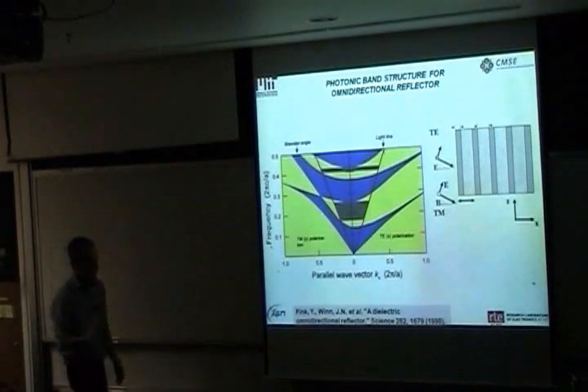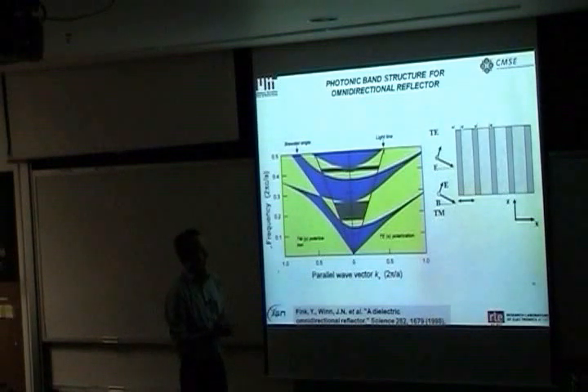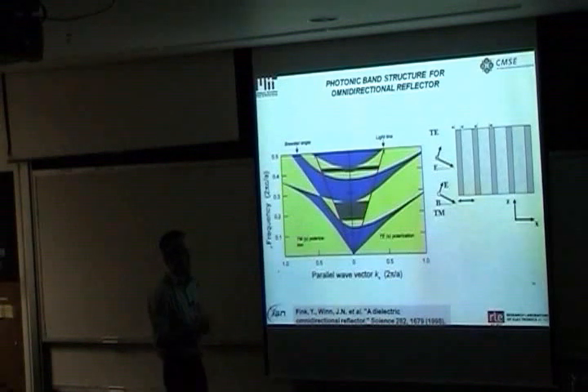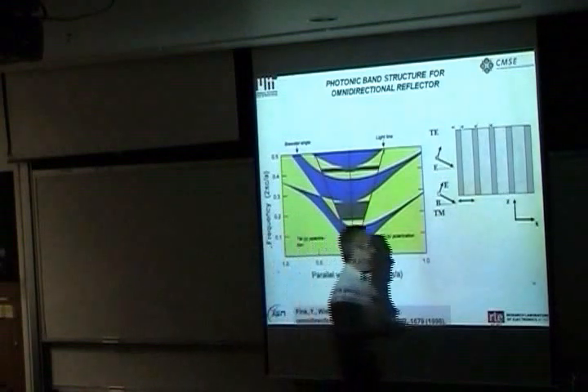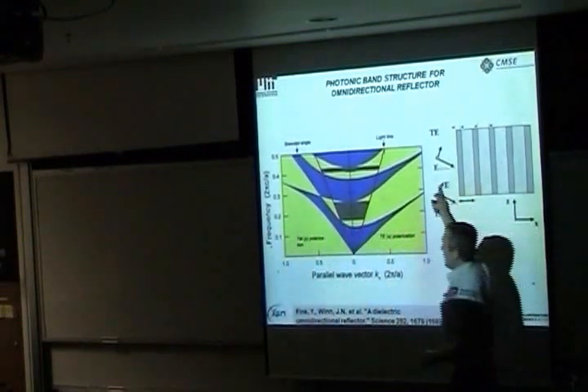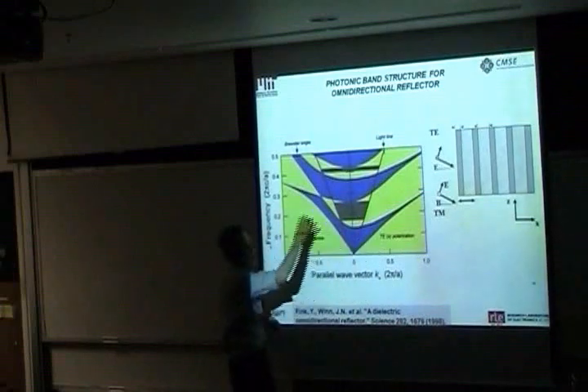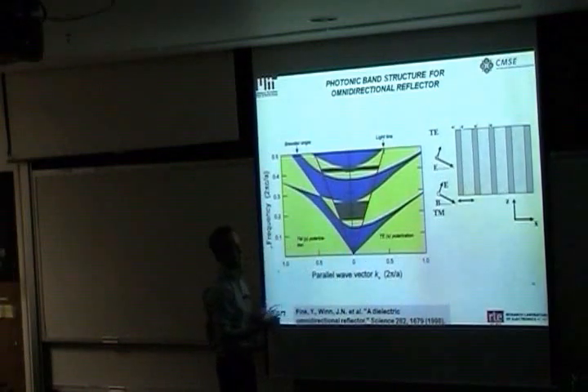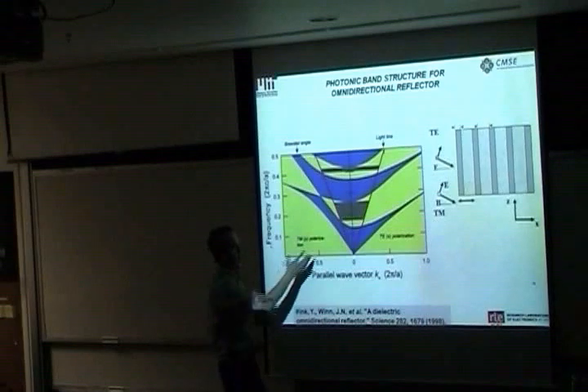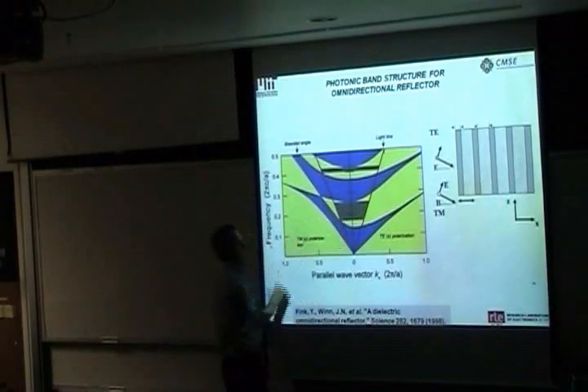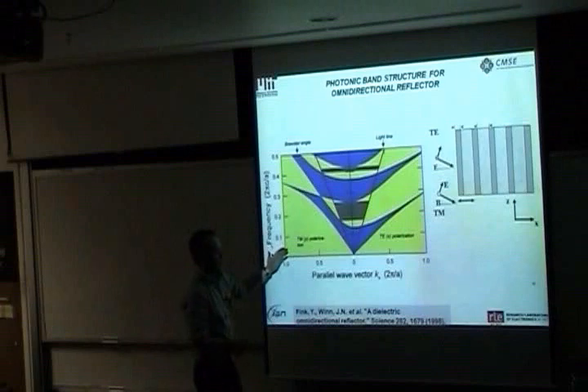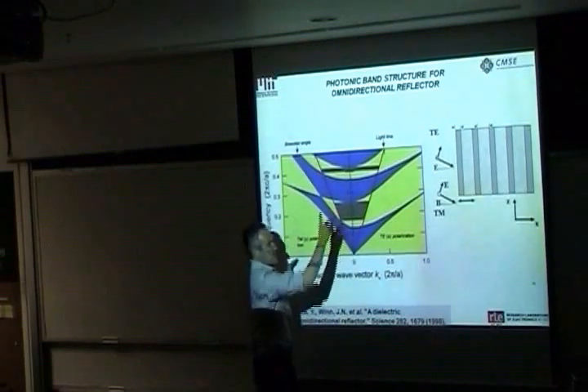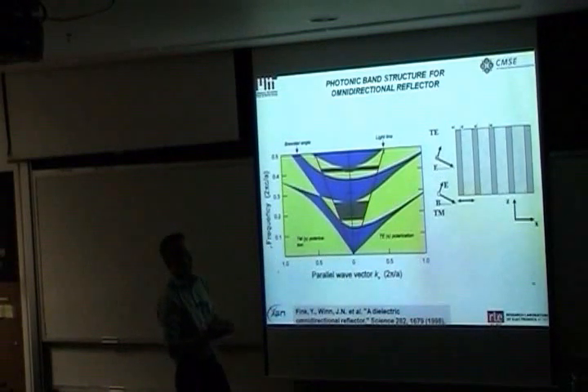And at the time, we figured out that, in fact, a one-dimensional periodic structure, while not having a complete photonic band gap, could still exhibit omnidirectional reflectivity, provided that the source of the light is actually in an ambient medium. And in order to achieve this omnidirectional reflectivity from a dielectric structure, one needed to generate a photonic band diagram that looks like this. So this is the frequency, this is the parallel wave vector, this is the component of the wave vector that is conserved in the z direction. This is the direction of